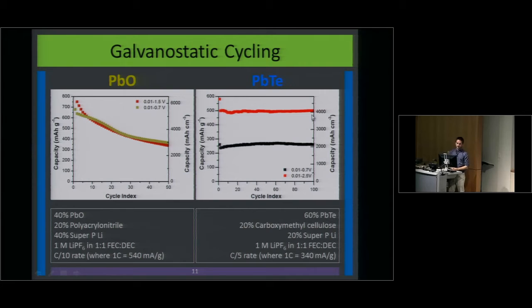With lead oxide, I did the 2 different voltage ranges and didn't get any difference in capacity. That's because that first reaction was irreversible. But with the lead telluride, it's not irreversible, so we actually get extra capacity out of there. And you can see that it's pretty flat for both.